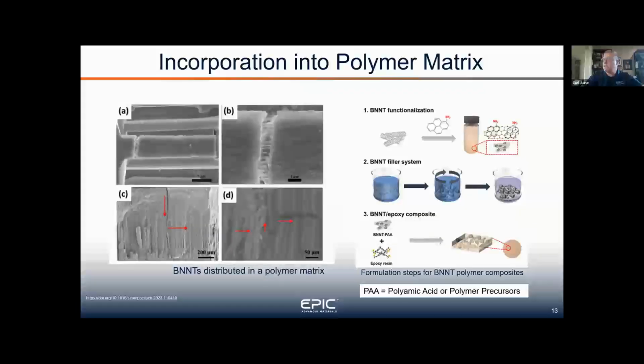So how are they incorporated into a polymer matrix? We functionalize the BNNTs using a plasma system. We add a chemistry that's dependent on the chemistry that it's going into, whatever that application may be. We then blend that together, mix it, catalyze, and you get your BNNT infused matrix that gives you those enhanced properties. As you can see in the image there, you get these bridging of the BNNTs through the matrix that improve strength, improve the thermal conductivity, and so forth.